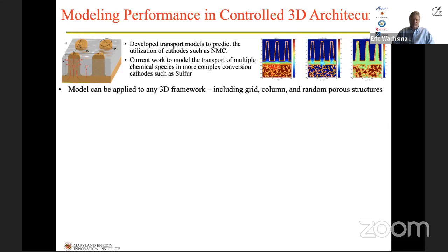The figure to the left would give you, again, an example of these columns of cathodes. We have the parameters of the diameter, the distance between columns and things of that nature. The red line's there to indicate the lithium flux that would occur. And the data to the right is actually then cycling data using the models as the lithium cycles back and forth between anode and cathode. These models we're developing can be applied to any 3D framework, including grid, column, and random porous type structures.